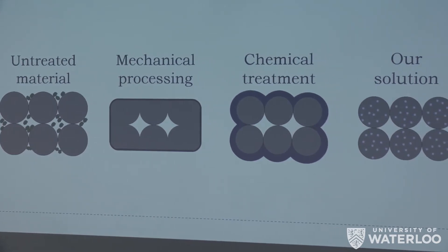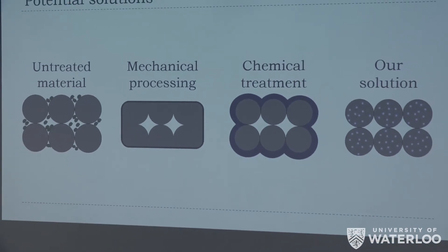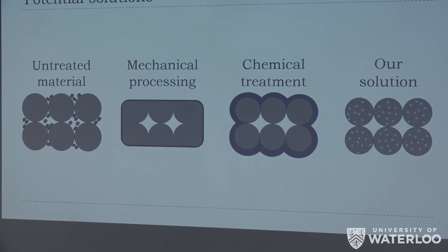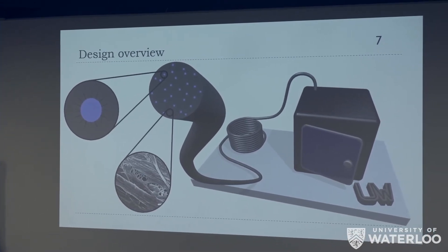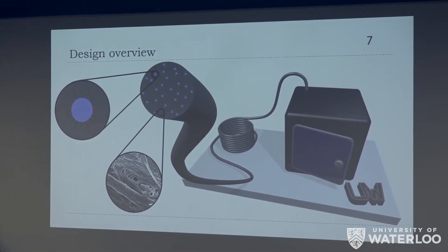For that reason, our solution is to incorporate our active material directly into the bulk, requiring no extra action from the user — they simply print using our material and the antimicrobial functionality comes right out of the box. With that in mind, we developed an antimicrobial material embedded within a polymer matrix, extruded this polymer into filament suitable for 3D printers, and verified functionality by running it through our 3D printer and performing antimicrobial and mechanical tests on finished products.